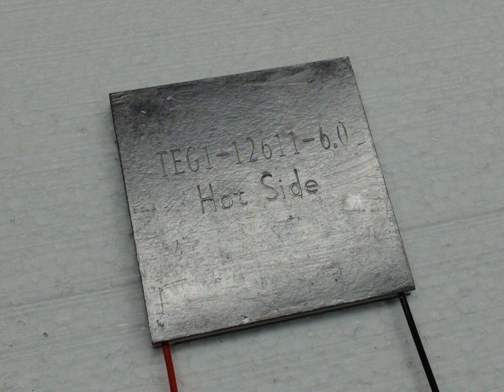When selecting materials for thermoelectric generation, a number of other factors need to be considered. During operation, ideally the thermoelectric generator has a large temperature gradient across it. Thermal expansion will then introduce stress in the device which may cause fracture of the thermoelectric legs, or separation from the coupling material. The mechanical properties of the materials must be considered and the coefficient of thermal expansion of the N and P type material must be matched reasonably well. In segmented thermoelectric generators, the material's compatibility must also be considered.